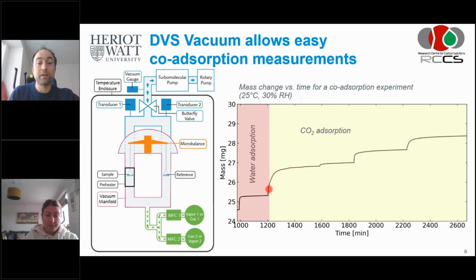So we have again a couple of set points on partial pressure. In this case, we have 1, 2, 3, 4. So we slowly increase the partial pressure of the CO2, and we let it equilibrate every time. So you see here that equilibrium is nicely reached. Here as well. And then we step on. So it's a relatively straightforward process, but, and I think this is really important,